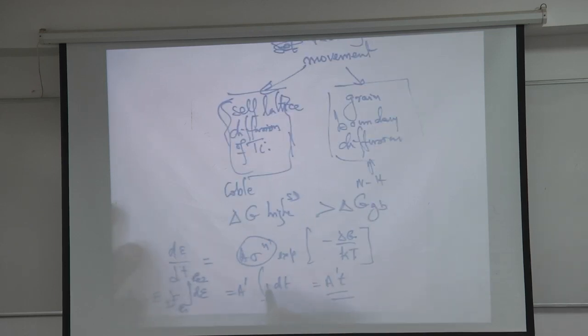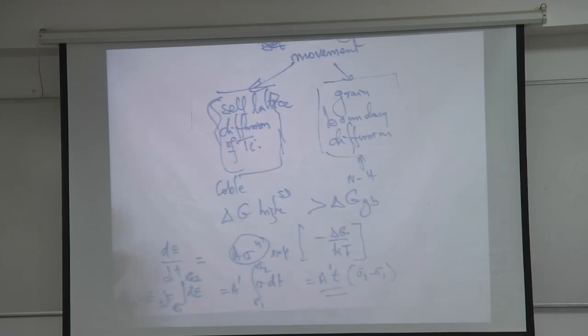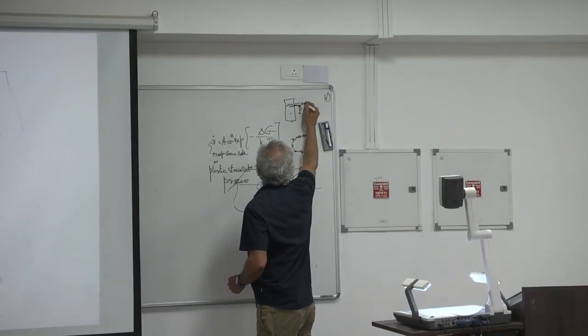I may have to put here sigma, maybe. I'm going to make something up. You said concentration gradient. True. I'm just going to put, if I have a little volume element here, this d epsilon that will take place in this volume element will be taking place because of a stress gradient, sigma 2, sigma 1, inside a small zone inside that component. So instead of a concentration gradient here, the vacancies are being driven by a stress-assisted diffusion.